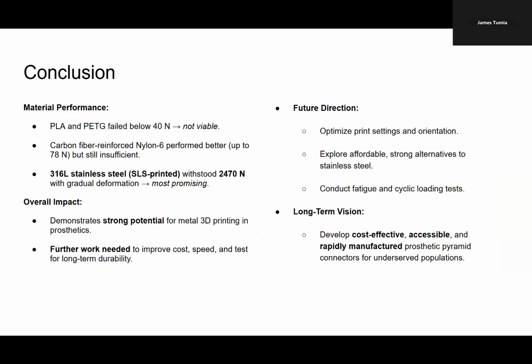On the other hand, the stainless steel pyramid connector printed using selective laser sintering performed exceptionally well. It withstood 2,470 newtons before deforming, and importantly, it didn't fracture at any point. This result supports our original hypothesis that SLS printed stainless steel could meet the static strength requirements outlined in ISO 10328. It also gave us a real sense of what's possible when advanced manufacturing techniques are applied correctly.